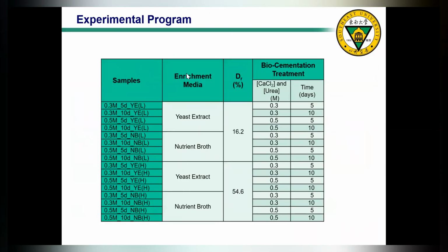So here is the overview of the experimental program, as you can see. We have 2 enrichment media. Then the soil samples are prepared at 2 different relative densities: one is low, 16.2%, the other is high relative density, 54.6%. For biocementation treatment, we selected 2 cementation solution concentrations, 0.3 mole and 0.5 mole, and 2 percolation periods, 5 days and 10 days. So this will give us different cementation levels.